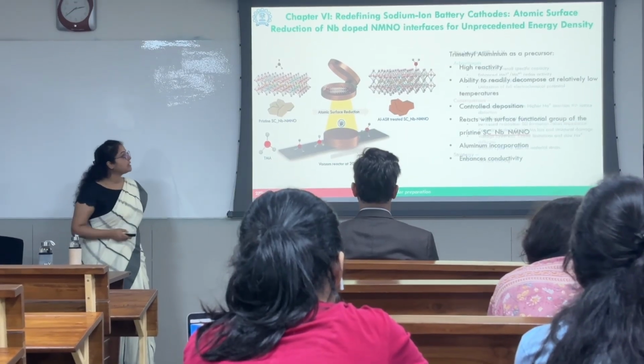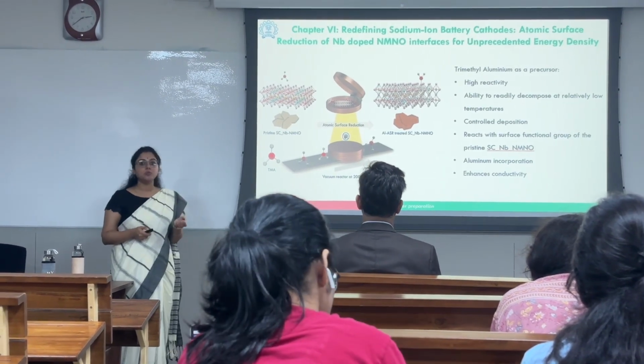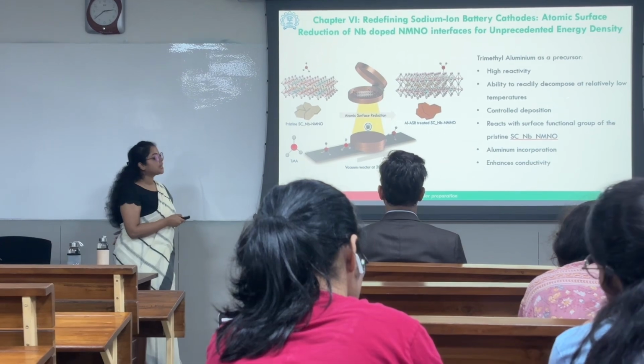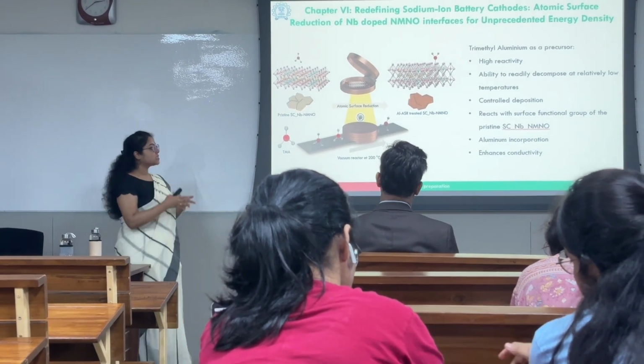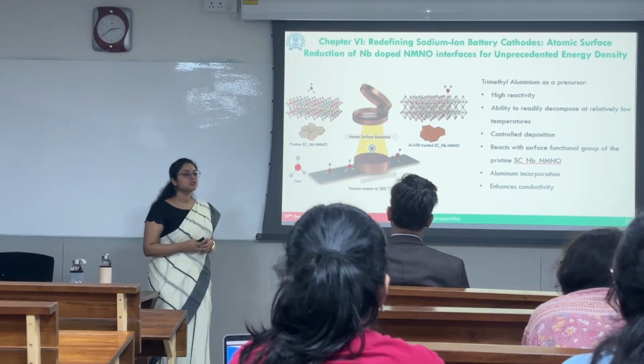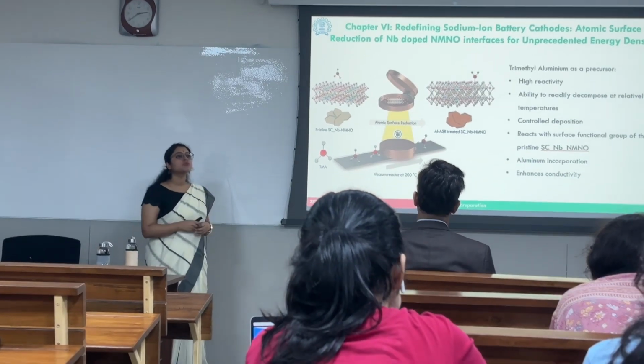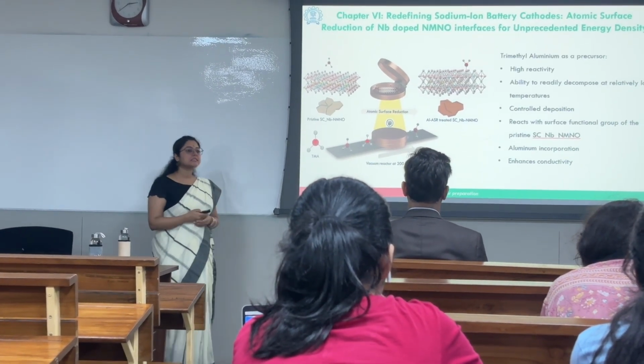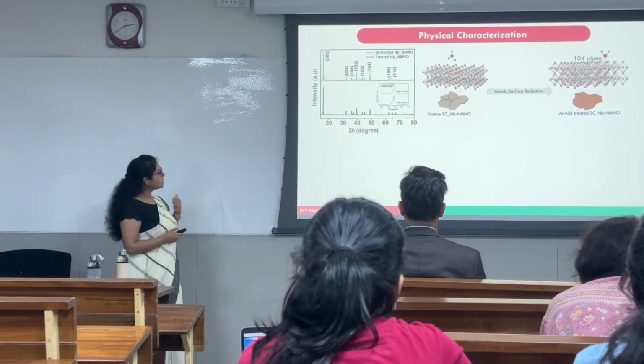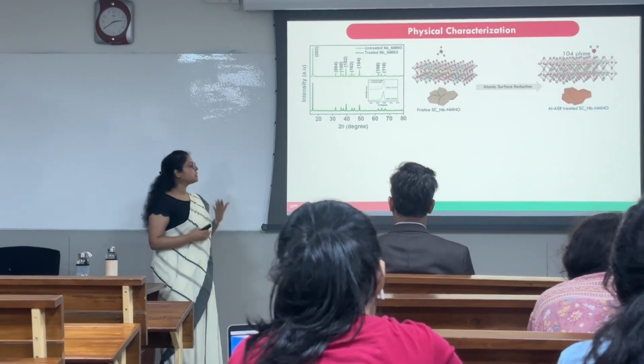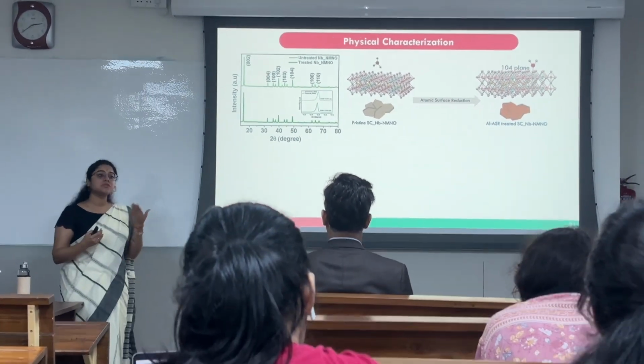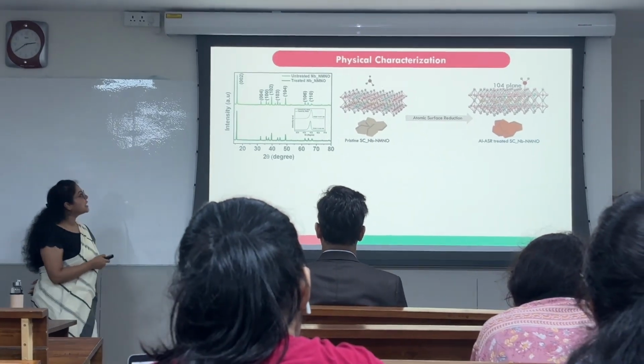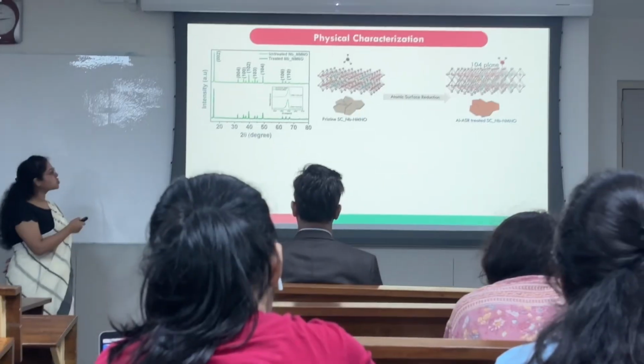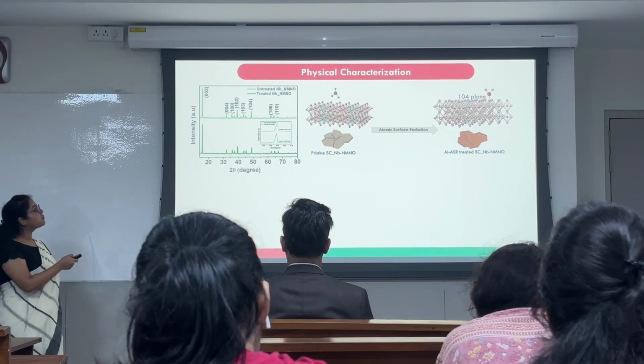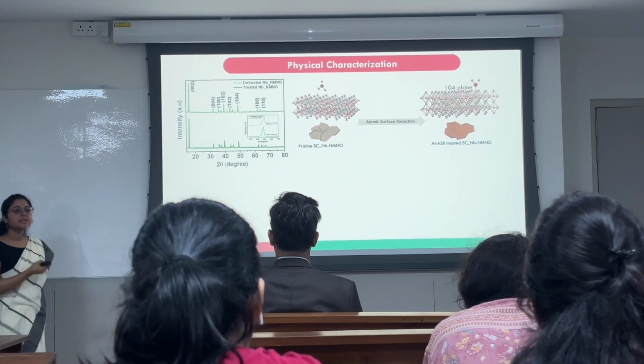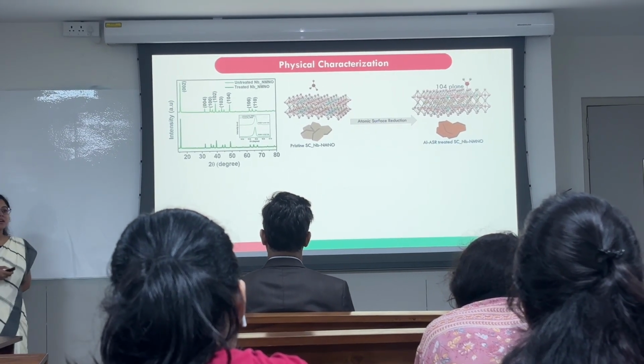So we start by choosing the trimethyl aluminum precursor because of its high reactivity and its ability to decompose at a relatively low temperature, also because it easily gets attached to the functional groups and thereby enhances the conductivity. We compare the XRD of the untreated and the treated material, and we observe that there's hardly any change in the bulk structure, except that the FWHM of the treated was narrower in comparison to that of the untreated one.